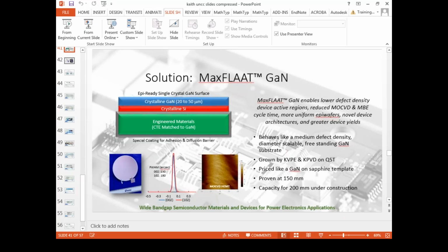You know, not that we understand all this. We think this is thin. I mean, certainly it's crystalline silicon, so there's a crystal surface to nucleate growth on, but we believe that it's compliant and moves as this expands as you heat it up and contracts with it as well, so that this stuff doesn't crack when we grow it on there. Now we can crack it, we have, so it's not completely strain free, but that's not a great answer, I feel like. We don't think the defect density is any lower than if you grew on a bulk silicon wafer. We've just rendered ourselves way less vulnerable to cracking and surface morphology.